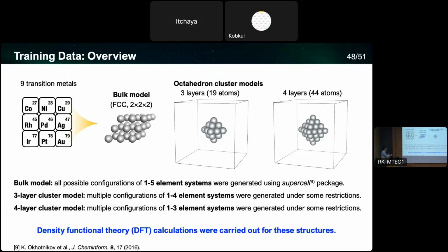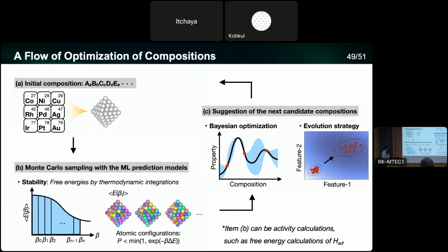And for clusters, it is extremely difficult to consider all the possible configurations. So we have some restrictions, and we have calculated multiple configurations, including up to 4 elements for the 3 layers clusters, and up to 3 elements for the 4 layered clusters. And we perform DFT calculations. The current progress will be introduced later by our student, but